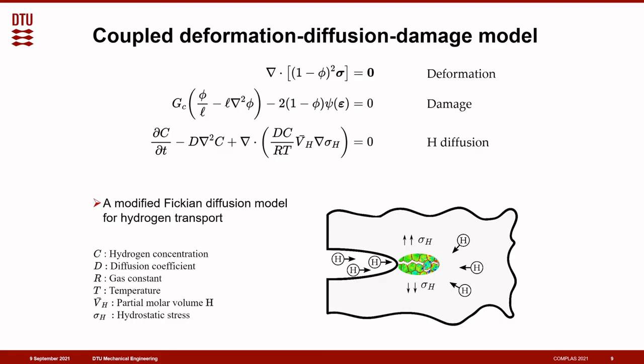The next step is to include the effects of hydrogen. It's a very challenging problem that crosses the disciplines of material science, structural mechanics, and chemistry. But in broad terms, what we know is that atoms of hydrogen enter the material, migrate fast through the crystal lattice, and are attracted to areas of high hydrostatic stress or high volumetric strains, where the lattice expands and there is more space for hydrogen to accumulate.